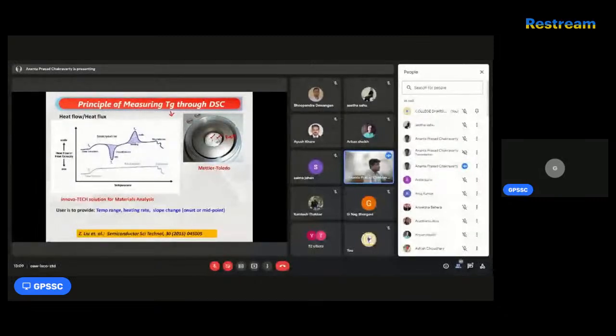where we will keep our samples within the probe dimension, and that probe can maximum accommodate 12 milligram of sample, and that dimension is obviously specified with respect to the probe. Now let us say this is our sample, and this is the reference sample, and it is thermocoupled. When you put some temperature, the difference in heat flow, that is known as heat flux, has to be taken care of.